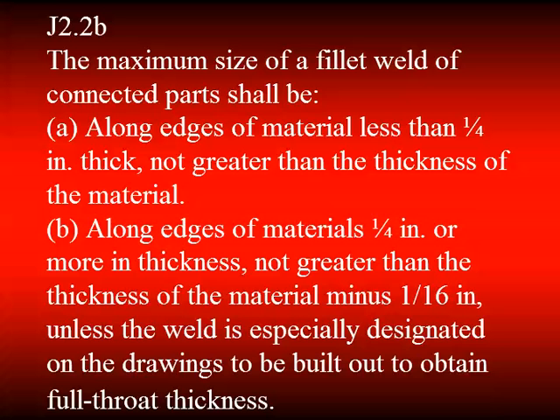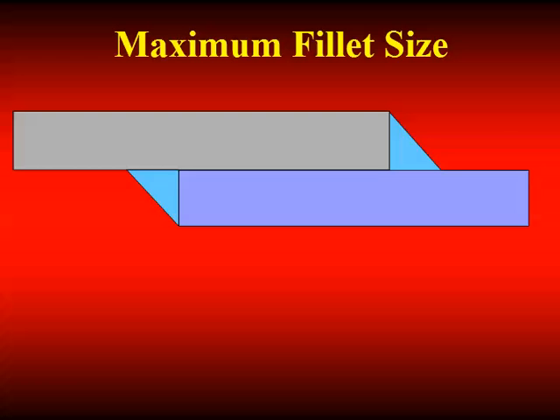Unfortunately, these provisions are subject to much misapplication, and so I want you to understand the proper intent. These words continue to be tweaked to hopefully get us closer and closer to the proper application. So let's read what J2.2b says. The maximum size of the fillet weld of connected parts shall be along the edges of material less than 1/4 inch thick, not greater than the thickness of the material, along the edges of materials 1/4 inch or more in thickness, not greater than the thickness of the material minus 1/16 of an inch, unless the weld is specifically designated in the drawings to be built out to obtain the full throat thickness. Now this is associated with lap joints.